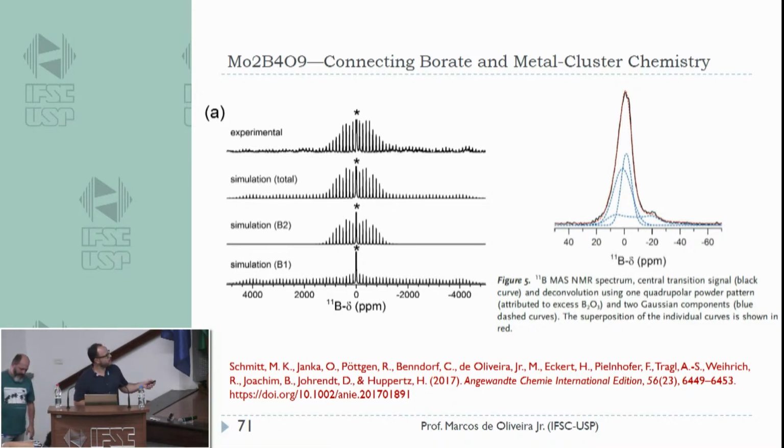Then if you look here, it's a low field spectrum. We have boron-3 lying down here, and we have two boron-4 species. And we couldn't resolve these two species if we didn't look at the spin sidebands. So we can see this is the experimental data, this is a simulation, and the simulation is done by assuming two different environments for our system.